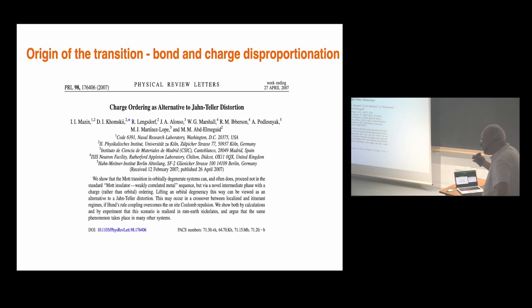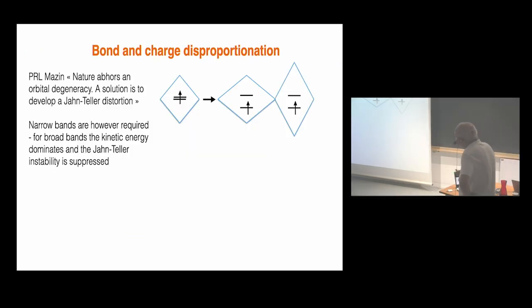And the origin of the transition was discussed in this important paper of Igor Mazin and co-workers. And the origin of the transition is this bond and charge disproportionation. So it's linked to this breathing mode. In this paper, they're saying nature abhors an orbital degeneracy, and the solution is to develop a Jahn-Teller distortion, what I just explained before. But to get this Jahn-Teller distortion, you need narrow bands. And if the bands are too broad, the kinetic energy dominates and the Jahn-Teller instability is suppressed.